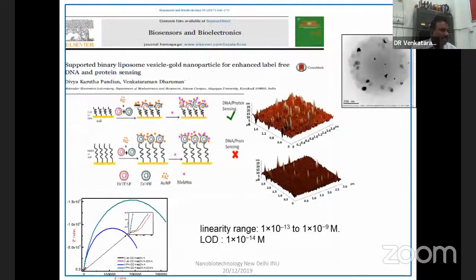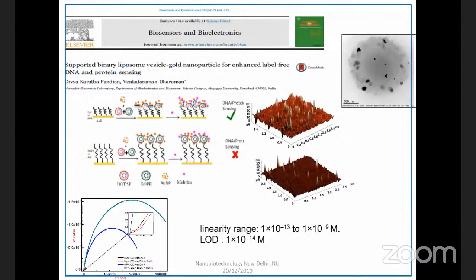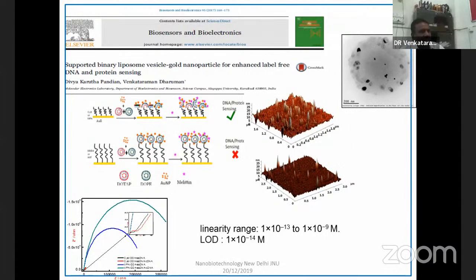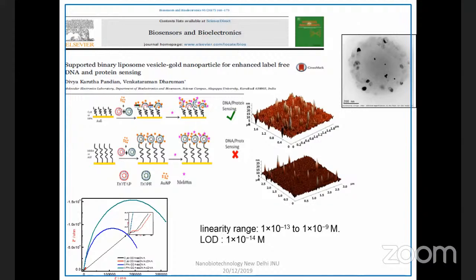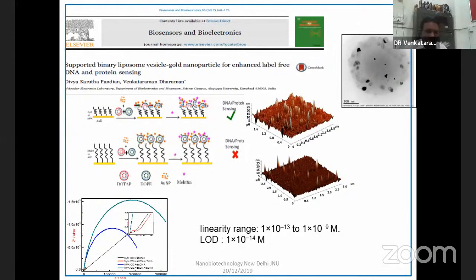Similarly, here we again combined two different lipids like DOTAP and DOPE mixed together. Again, the same protocol was used, confirming the attachment of a lipid layer on the surface, and we put a single strand and a double strand. Single strand is this one, lower resistance, and double strand is this one, higher resistance. And here the concentration linearity range we obtained is from femtomolar to the nanomolar range, and the lowest detection limit is 10⁻¹⁴ molar.